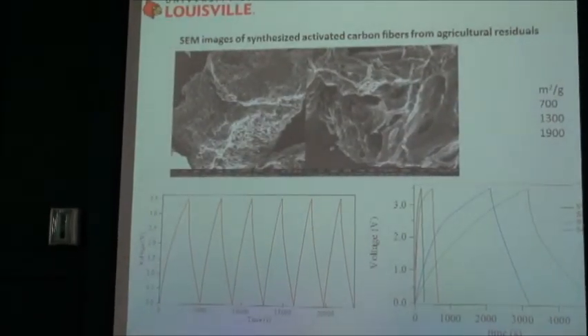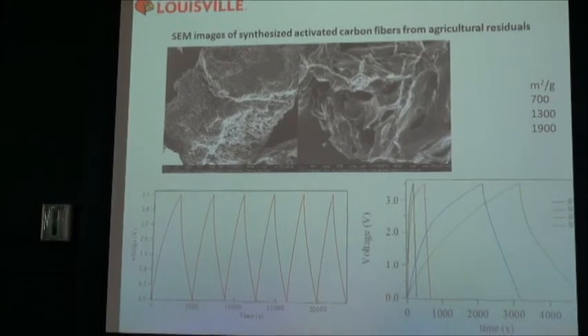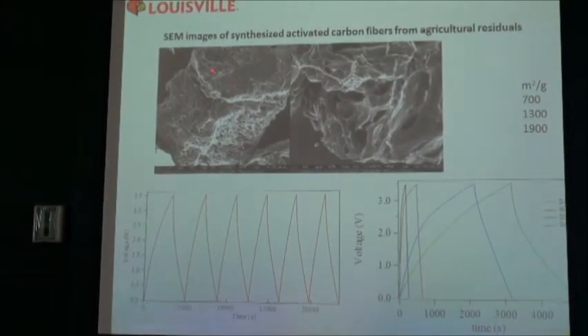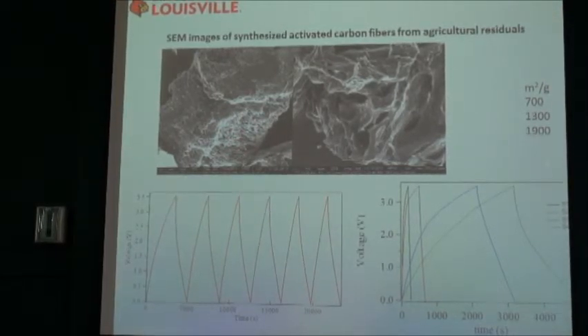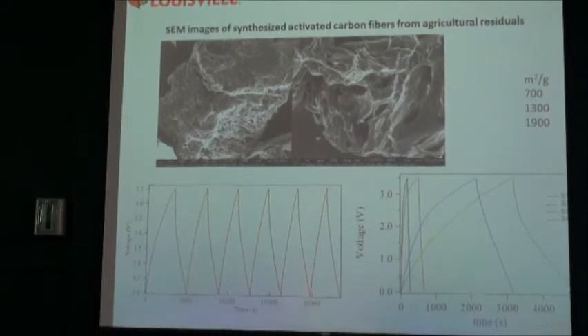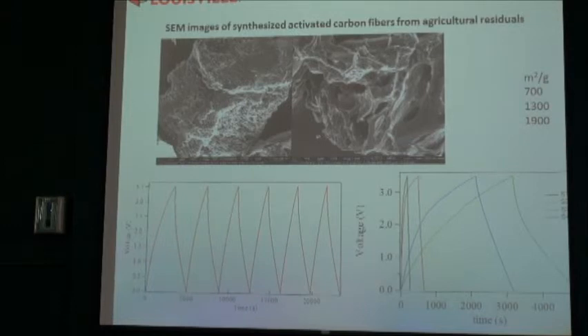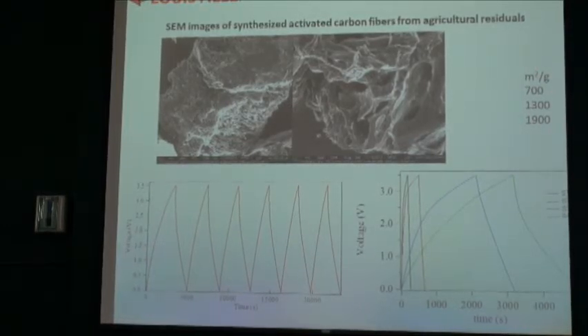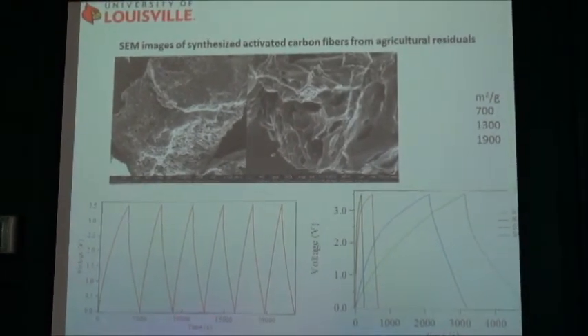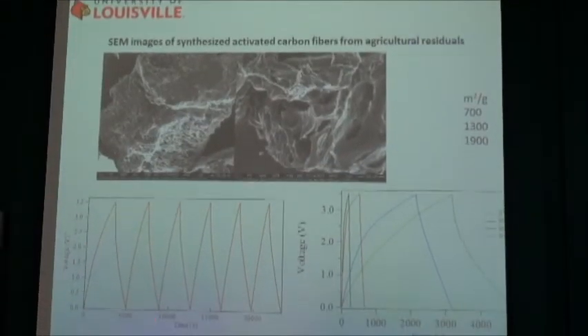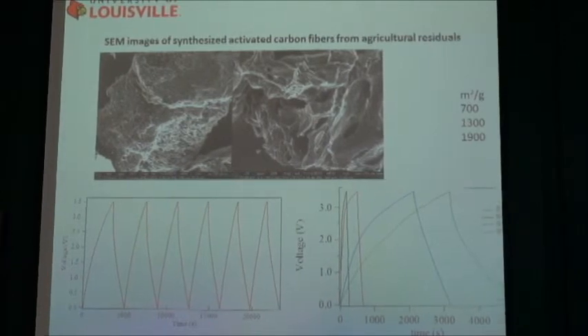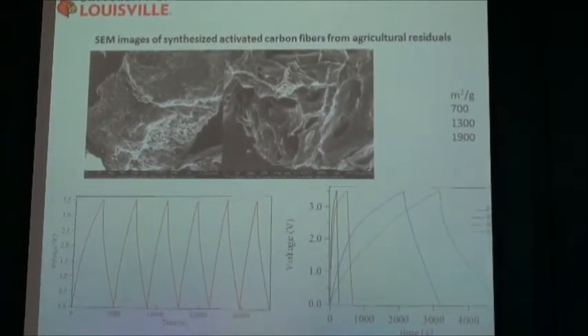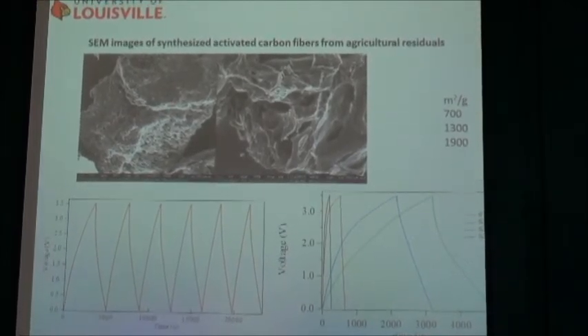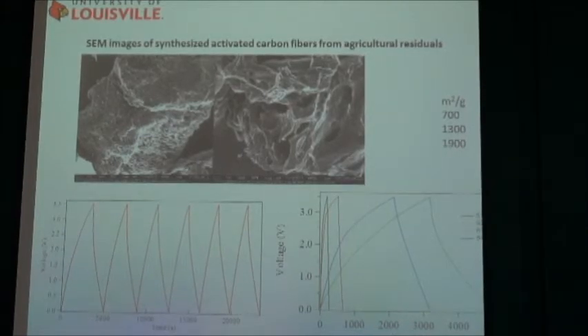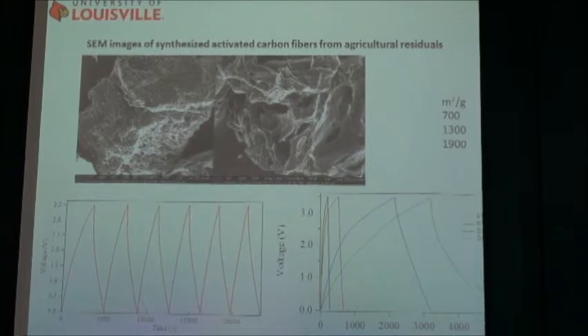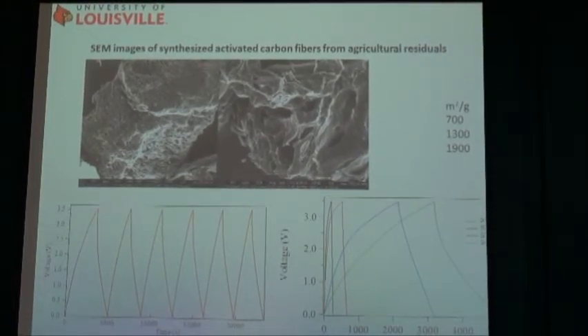These are some of the features of the carbon fibers. If you look at this, they have these small pores, micropores and mesopores. That's why they give very large surface area. Initially we got about 700 square meters per gram. Then, by changing the parameters, we are now getting close to 2000 square meters per gram. Then when we look at the charge capacities, this is how we calculate the capacity. In typical electrostatic capacitors, the capacitance is typically in microfarads or nanofarads, small capacitors, right? But with these you can get farads, even kilofarads.